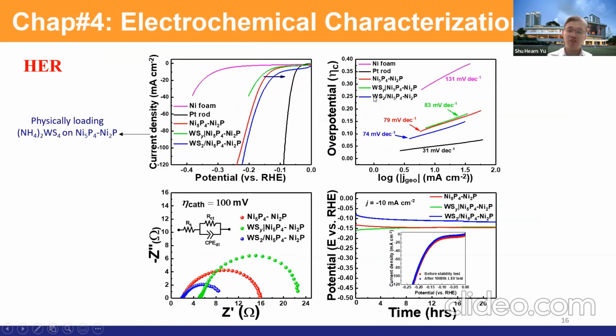Then we carry out the HER performance, the electrochemical characterization. We also have one control sample. For example, we have the WS2 precursor loaded on the nickel phosphide without doing any thermal treatment. I denote it as WSx because I'm not sure about this stoichiometric ratio. We find that the black color is the platinum rod, and the blue color is our hybrid sample.